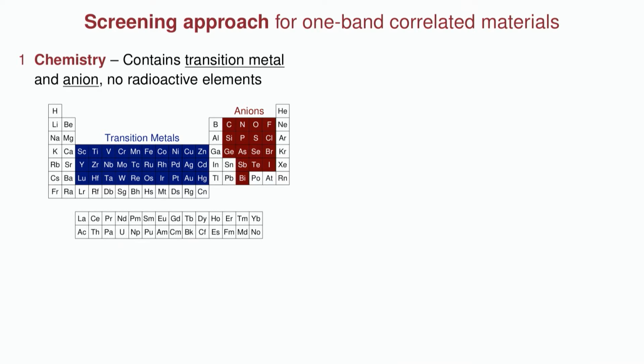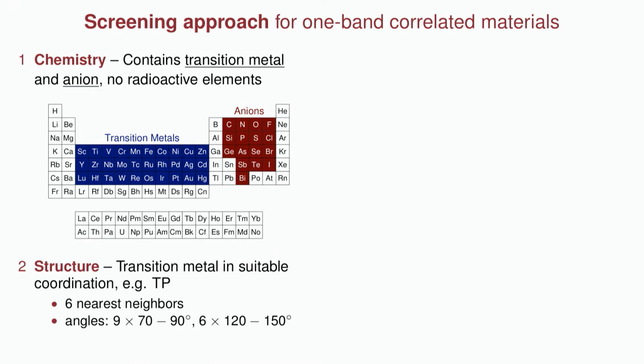So first of all, we consider chemistry. So we're going to want something with a transition metal coordinated to some anion. We're also, to be practical, going to ignore anything with radioactive elements. That's not so interesting to us. Secondly, we're going to look at the local structure, so that coordination environment of the transition metal. So we want some suitable coordination such that the symmetry is broken enough that, in principle, we can have one isolated d orbital. So, for example, there are several of those, but one of them is just that trigonal prismatic we just talked about. And so there you just want 6 nearest neighbors and these particular bond angles corresponding to that kind of shape.